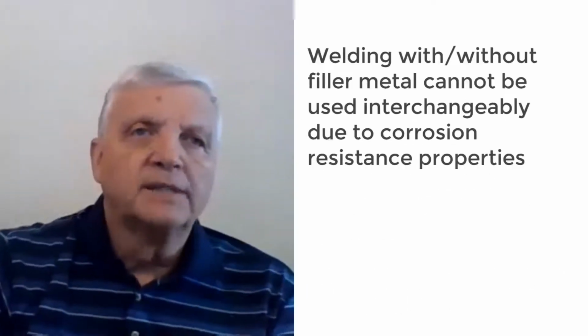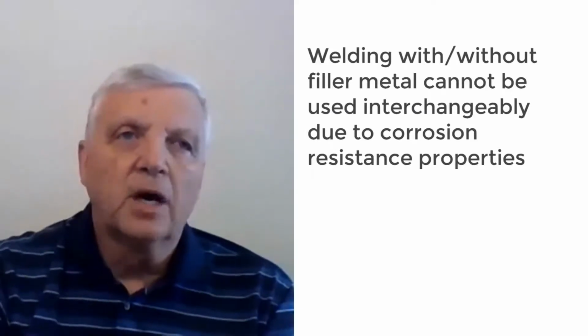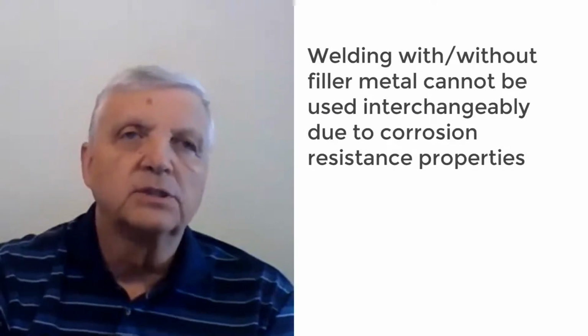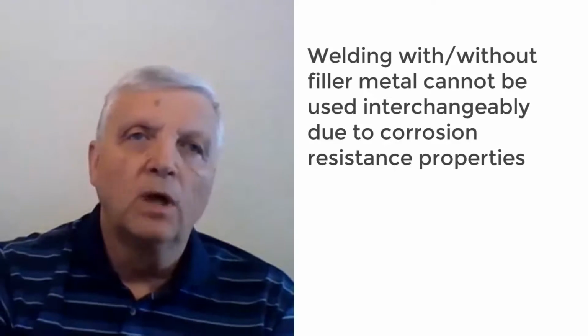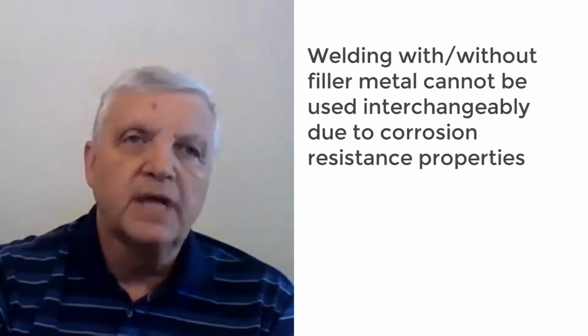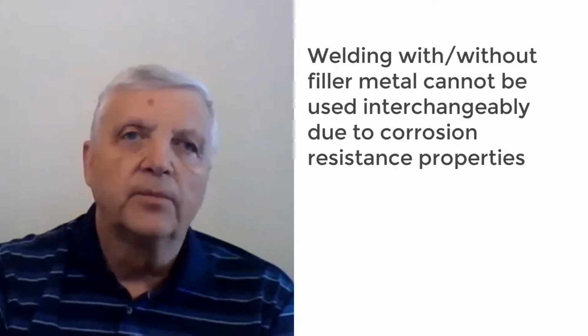It must be realized that welding with or without filler metal cannot be used interchangeably in all instances, as it will not always produce weld metal with equivalent corrosion resistance and/or physical properties in comparison to the starting metal. As stated previously, there is no significant visual difference between the two types of weld, but there is a significant microscopic difference. As is, weld metal possesses a cast microstructure in contrast to the wrought microstructure of the starting metal.